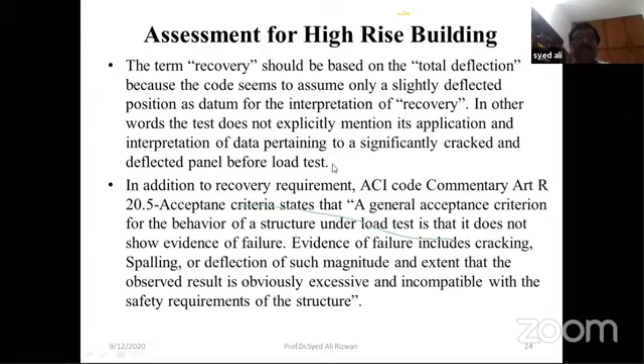In addition to the recovery requirement, ACI Code Commentary, Article 20.5 acceptance criteria states that a general acceptance criterion for the behavior of a structure under test load is that it does not show evidence of failure. Evidence of failure includes cracking, spalling, or deflection of such magnitude and extent that the observed result is obviously excessive and incompatible with the safety requirements of the structure.